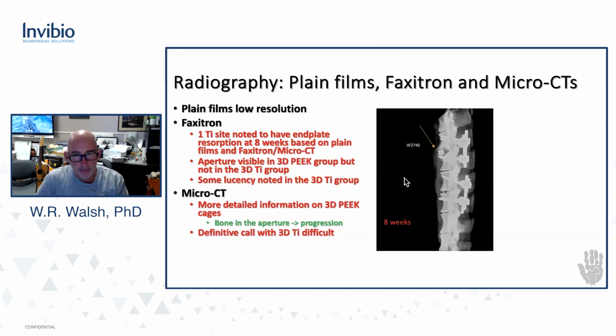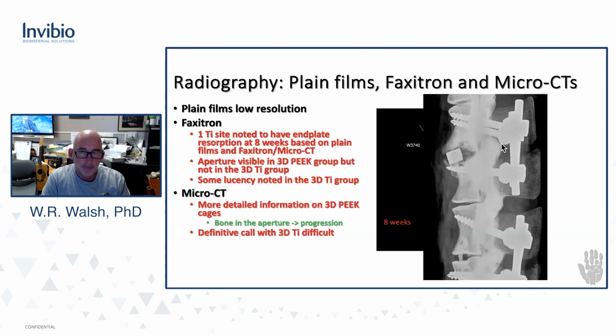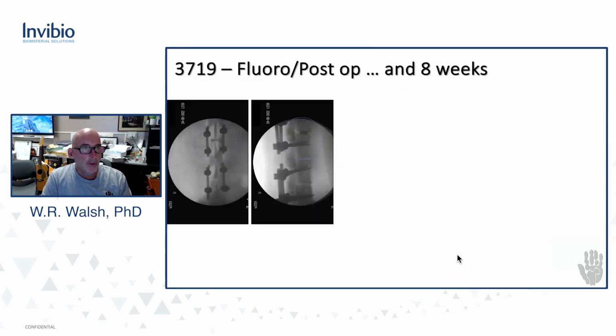This was the case that had a titanium cage that was unfortunately infected, and we'll revisit that later. And there's the corresponding PEEK cage at 8 weeks where we can actually see the graft in the aperture, and we can even see a hint of osseointegration there. So if we look at this as a case that we did, this is the post-op fluoro.